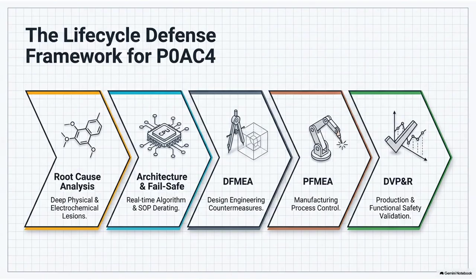Okay, but the second failure mode in the chemical layer is far more insidious because it represents permanent, irreversible degradation. What happens when the athlete isn't just cold, but is chronically overheating? Right, so high temperature operation, especially when combined with high C rates, and by that I mean aggressive rapid charging and high power discharging, that fundamentally alters the chemical makeup of the cell. You're literally cooking the chemistry. You are. At elevated temperatures, the delicate thermodynamic equilibrium of the cell just breaks down. The primary victim here is the solid electrolyte interface, or the SEI layer, on the anode, alongside the actual electrolyte itself.